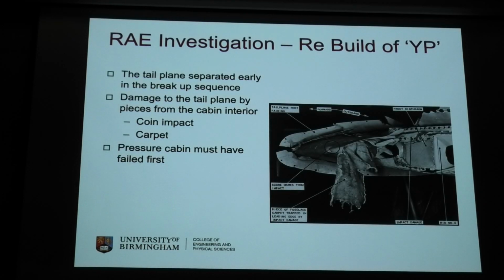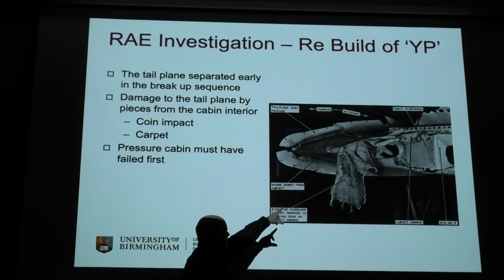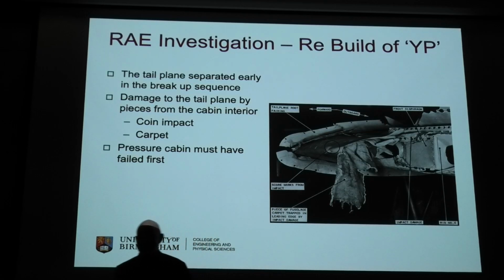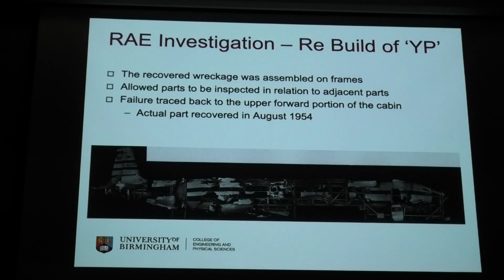The tailplane seemed to separate early in the sequence, but there was damage from coin impact and, to an extent, the internals of the cabin. So you can see score marks, there's a coin indent, and there's a piece of the carpet stuck in the leading edge of the tailplane. That obviously came out of the cabin before the tailplane broke away, so some kind of sequence was being built up based on the damage that they were finding. And score marks across cracks, those cracks couldn't have occurred and the score marks be continuous across them. So there's all sorts of things happening.